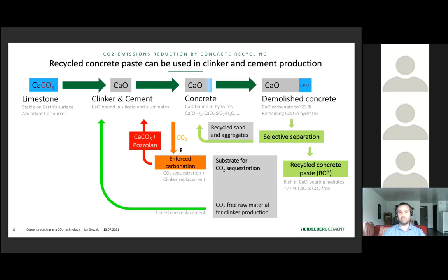So in fact, this is a carbon capture technology based on recycled material. And that's not the end of the story, because there is not only calcium oxide in the cement hydrates, but also silicon and alumina. These two components get activated by the carbonation and turn into a reactive material, which can be used for cement production. So at the end, after the carbon capture, we take this carbonated RCP, we blend it with freshly produced clinker, and we have a new generation of high quality cements for structural concrete application.